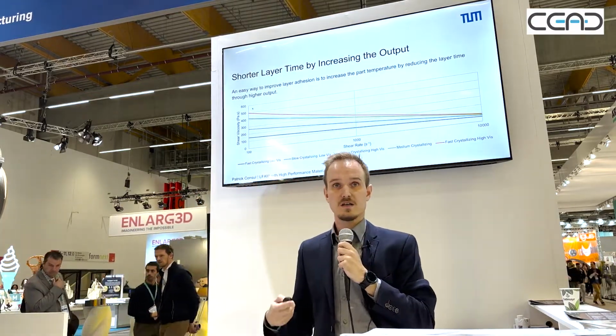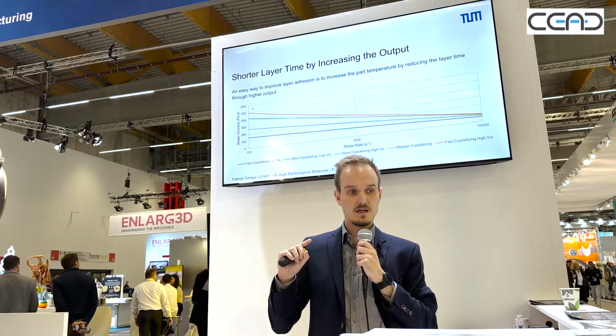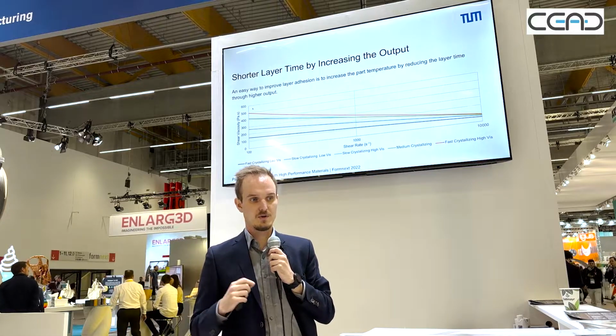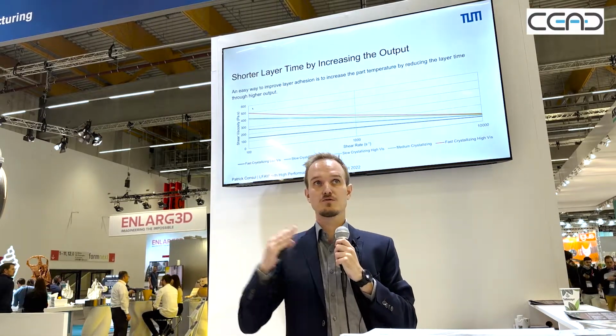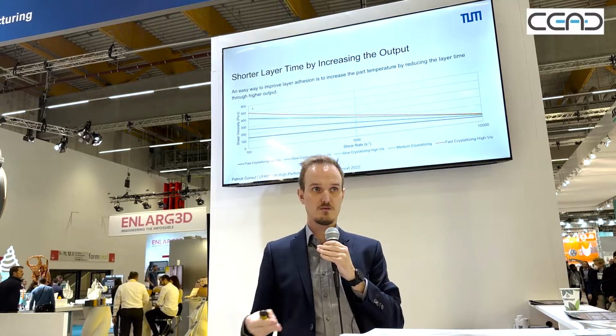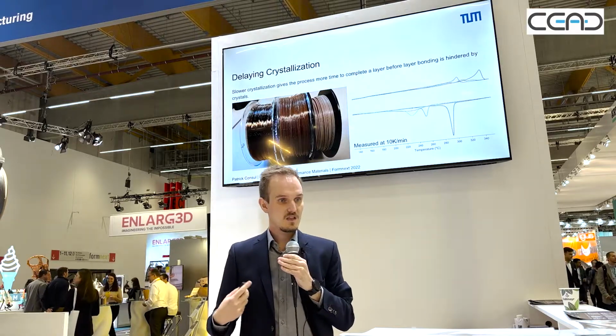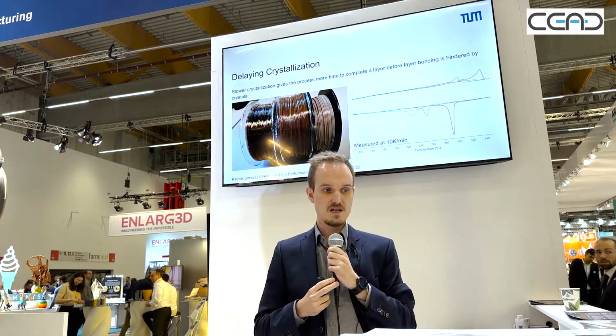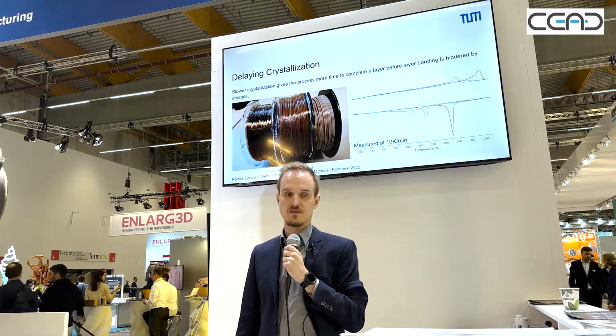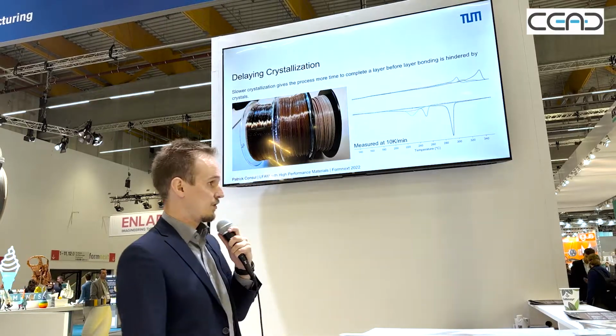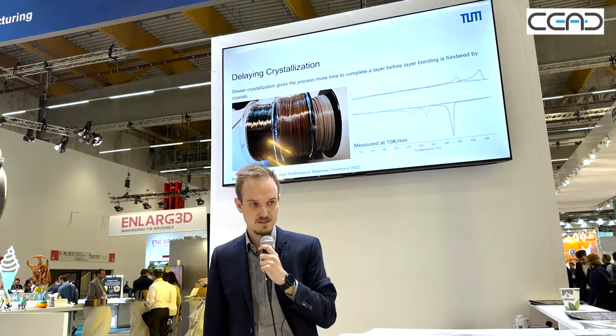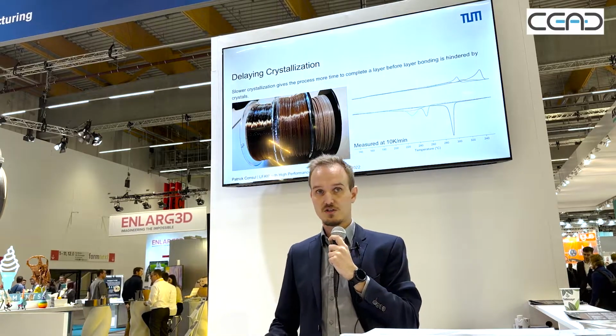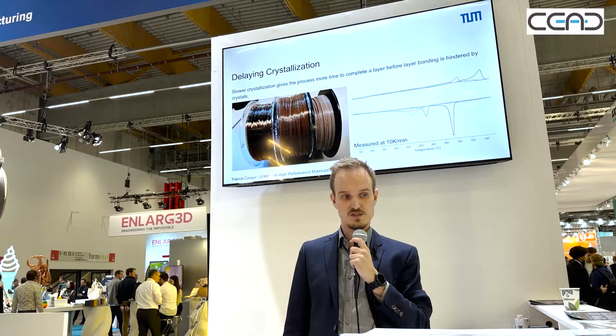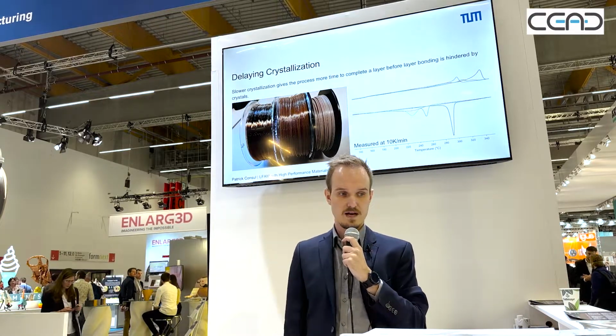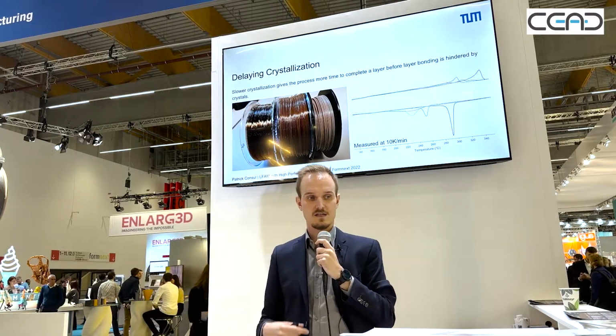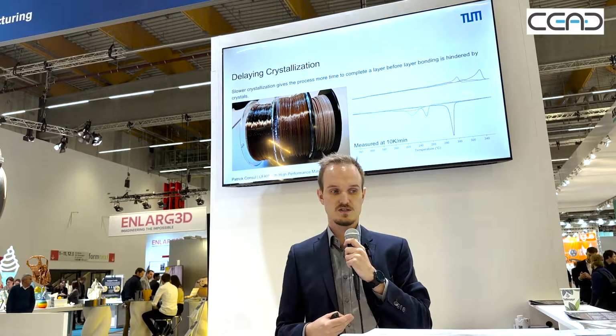Which brings me to my next point, the crystallization speed. Once we've maximized the output and we can print as fast as we can, the other trick is to just increase the time that the polymer needs before it's not bondable anymore. And Victrex actually has a couple of different PAEKs in their portfolio which crystallize at different speeds. This is from one of the earlier material trials when we were still using filaments, but it shows my point quite nicely. They're all manufactured the same way, and the one on the left is almost fully transparent, while the one on the right is completely opaque. And it just shows you how differently they crystallize. The opaque one is fully crystalline, and the transparent one is amorphous.